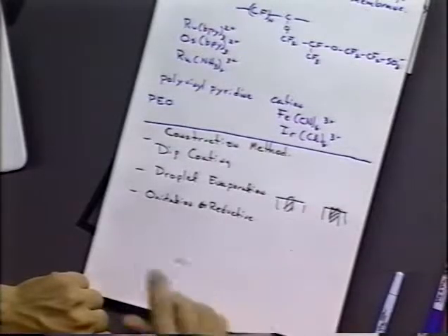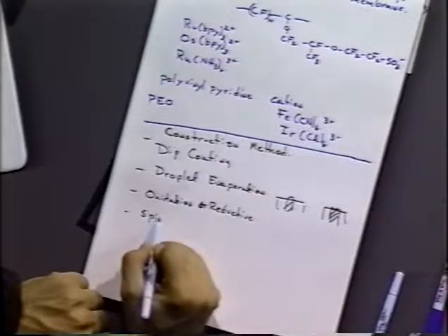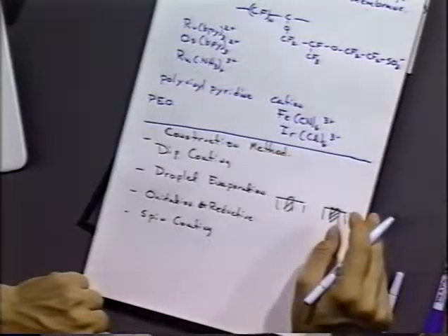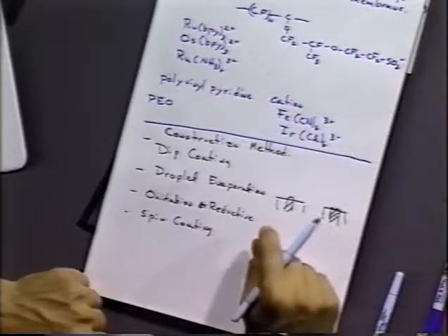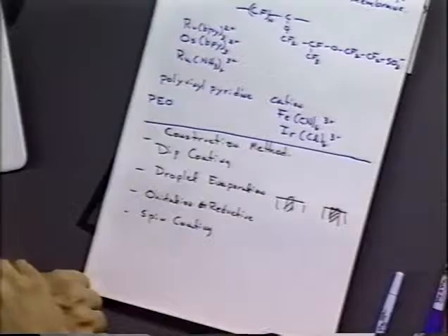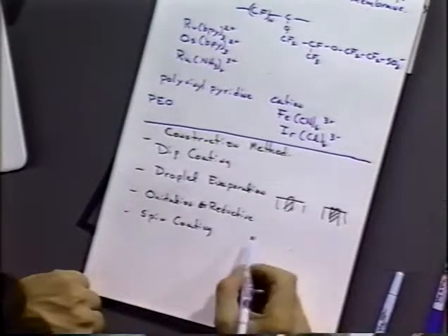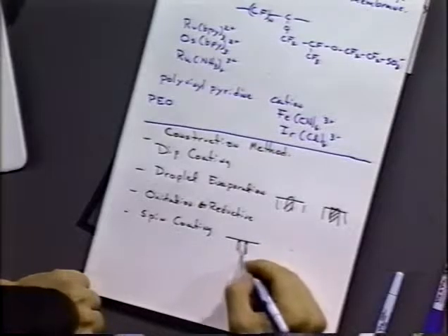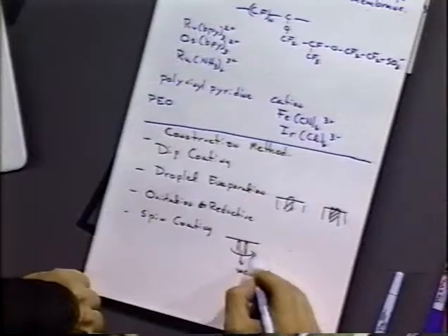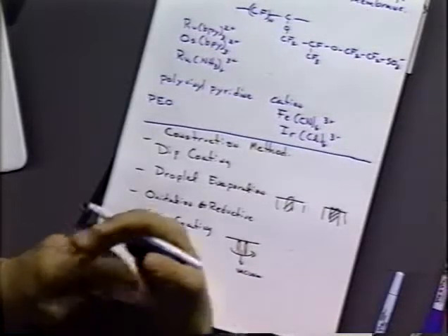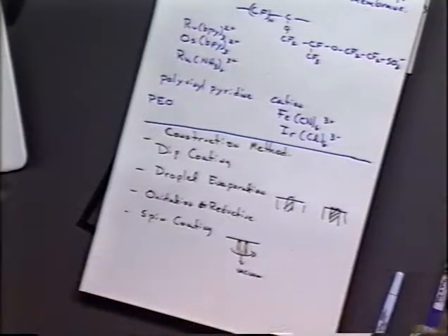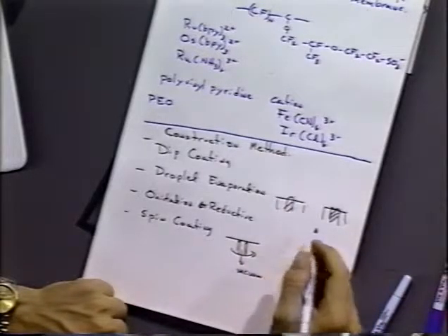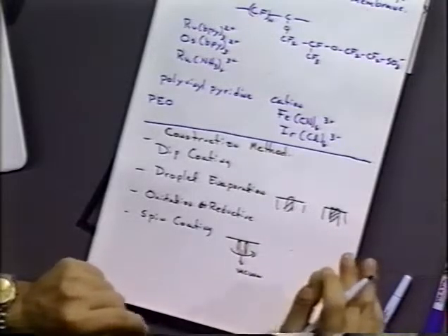Oxidative or reductive deposition is another method — for example, polypyrrole is an oxidative process, and polyaniline can be made by oxidation of aniline. A very common and good method is spin coating. It requires a spin coater — essentially a spinning chuck. You put your electrode on top, held down by vacuum via an O-ring, and it spins at a certain revolution per second. You add your material at a certain rate and centrifugal force sprays the material out, leaving behind a pretty uniform film. This is a nice way to make films that are particularly uniform in thickness.